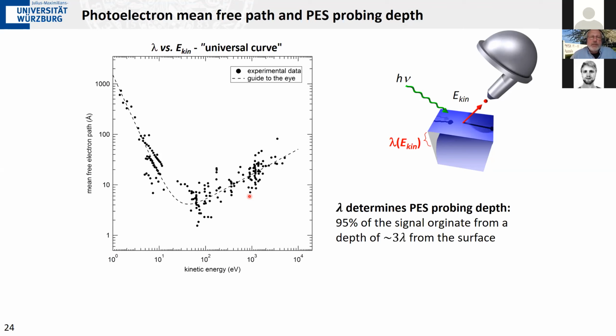By that, these electrons, the photoelectron, will lose energy and forget about the original energy information that I wanted to measure. And there's only a certain fraction of photoelectrons that ever reach the surface without having undergone such an inelastic decay, or an inelastic collision. And it turns out that the probability with which such a photoelectron can interact with the other electrons depends on the energy, or you can turn this into a mean-free path. The distance an electron, the photoelectron, can travel without undergoing such a transition. That's called the mean-free electron path.